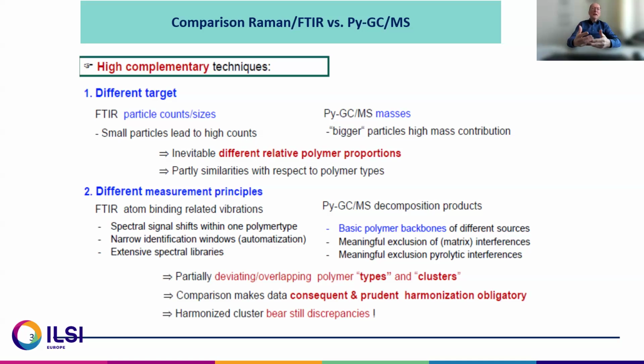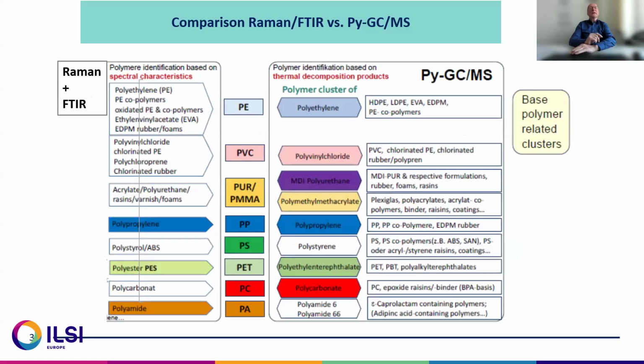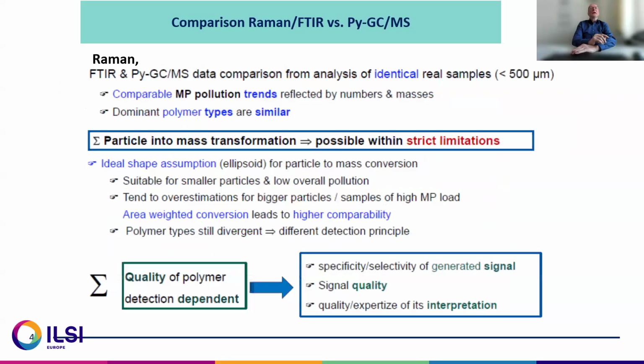And the next is, I told you about these clusters: in the spectroscopic methods we could clearly identify every polymer, but in the pyrolysis only the clusters, and we have to harmonize these clusters for a better comparison. This is an idea how we can do that. On the right side are the clusters for pyrolysis. On the left side, all the polymers from Raman and FTIR, and in the middle, we build clusters so that we can compare this data. So how can we do that?